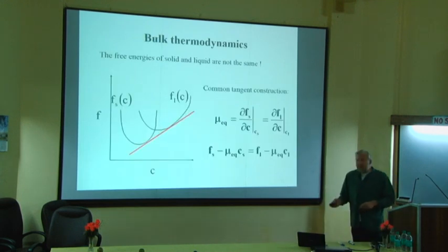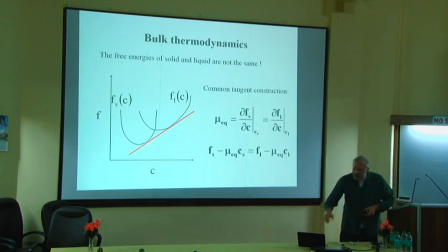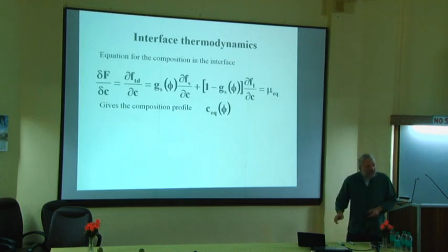Equilibrium thermodynamics just fixes the position of these 2 points. So it tells you this function is the same in the 2 equilibrium phases. If you want a well-behaved phase field model, you need a stronger condition. You need that the profile through the interface actually goes exactly along the red line, because through the whole interface, f minus mu c should be a constant.